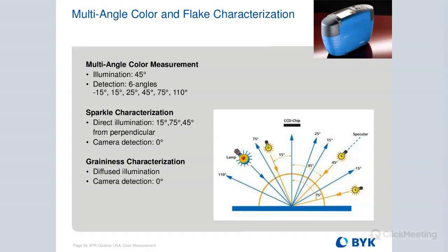So if you make these different ladders of concentration of pigment and you combine them with different colors, you can see visually how you can cover certain areas of color space. If you wanted to use a database to do that, you could do it the old-fashioned way and just make a bunch of different formulas and do visual comparisons. We do have software that will formulate for effect pigments. And in that case, similar to building a ladder, we give you instruction on how to let the different pigments down with combinations of white, black, and different effect pigments.